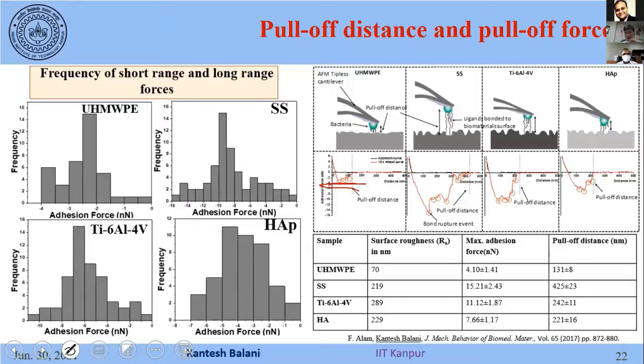So you can see the maximum adhesion force is of the order of 7 or so nanonewton, which means already in the interaction regime. Whereas for polymer, the maximum force is only 4, which is transition to the interaction regime. So they may still be in the planktonic regime for a lower duration. The pull-off distance also is much lower, meaning they are still trying to interact, and they are still in that regime.